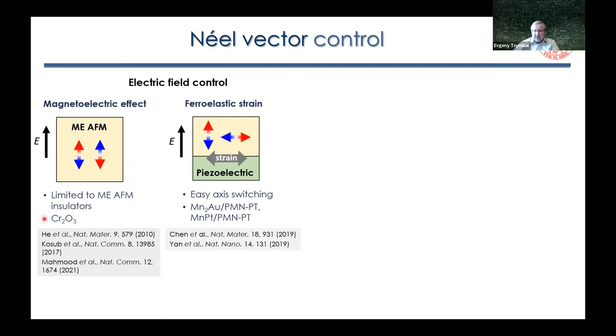In particular, that has been nicely demonstrated for chromium oxide (Cr2O3) in a set of publications listed here. Alternatively, we can use piezoelectric materials by combining antiferromagnets with piezoelectrics, like, for example, well-known PMN-PT, which produces in-plane strain under the application of perpendicular electric field, and that may produce change in the easy axis and rotate magnetization.